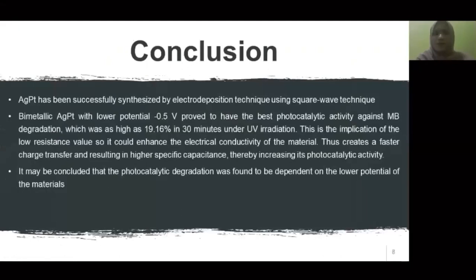So, AgPt has been successfully synthesized by the electrodeposition technique using square wave. Bimetallic AgPt with lower potential minus 0.5 volt proved to have the best photocatalytic activity against methylene blue degradation, which was as high as 19.16% in 30 minutes under UV radiation. This is the implication of the low resistance value, so it could enhance the electrical conductivity of the material, thus creating a faster charge transfer and resulting in higher specific capacitance, thereby increasing its photocatalytic activity.